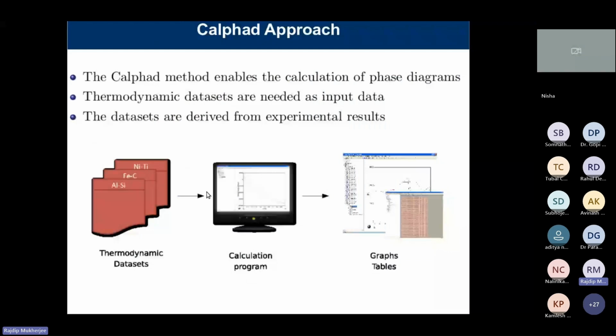So the CALPHAD method enables the calculations of phase diagrams. Unless you know the phase diagram of an alloy system, you cannot simulate what will be the microstructure, right? So the phase diagram and the free energy diagram, these are the two important thermodynamic data sets we need to simulate the microstructure evolution. The kinetic data set is also important because how quickly it is going towards the evolution, meaning what will be the time scale, that is important, because if you don't know the diffusivity value, you cannot tell what will be the effect of temperature, right? With increasing temperature, the diffusivity increases in an exponential manner, right? So those things we can get using the CALPHAD approach.